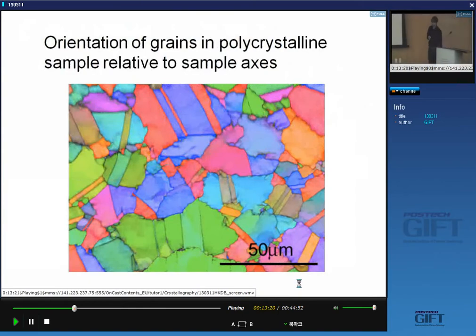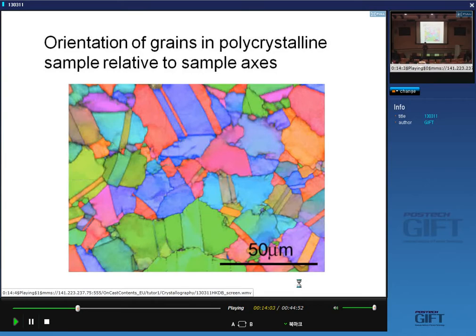You've seen many diagrams like this in our department, where the color actually represents the crystallographic orientation. But you also have sample axes. So for example, this might be a rolling direction and this might be the transverse direction. So you can plot the crystal orientation with respect to the sample axes to show you the distribution of orientations, because we very rarely have materials which have a random distribution of crystals. Normally they will be aligned in some way because you've deformed it, you've heat treated it, transformed it in a magnetic field or whatever. It's very difficult to produce a material in which the crystals are distributed randomly.